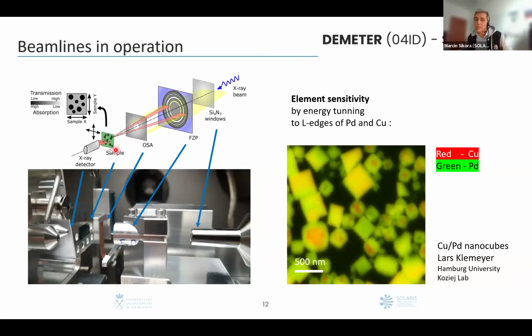And we scan our sample, like in a classical electron microscope, and we can measure both in transmission, and we are also now developing fluorescence and ptychography. So that's basically a technique that provides similar information to electron microscopes, but with better chemical sensitivity. One example is these nanocubes of palladium that were filled with copper inside. And you can really see with this microscopy that indeed you see the copper inside many of these cubes that are the sample in the solution.